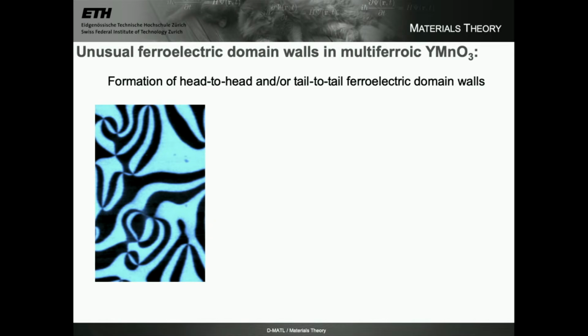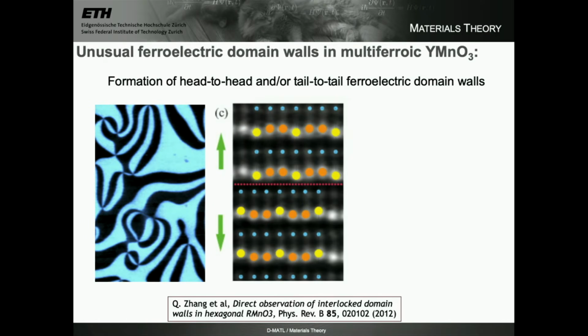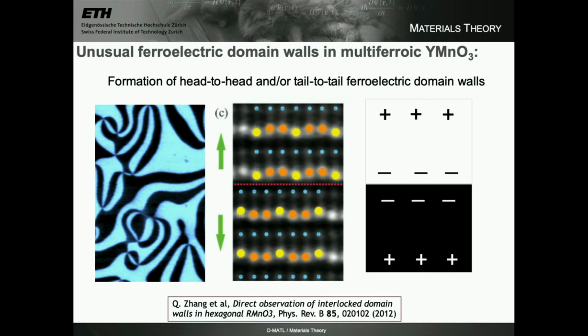And so if you think about this for a little while, here's a blow-up of one particular region. In this region here, say, the ferroelectric polarization might be up, and in this region here, it might be down. And here's a high-resolution microscopy image again. This is not from our group, but the group of Zhang and co-workers. This is this domain wall, this intersection between these up and down regions of polarization. You can see it's a very sharp interface, and the up polarization is marked by a kind of up-up-down pattern of the yttrium ions, and the down polarization by a down-down-up pattern. So we see that there's a change from up to down at that line. If you think about this for a moment, electrostatically, this is a very unhappy domain wall, right?